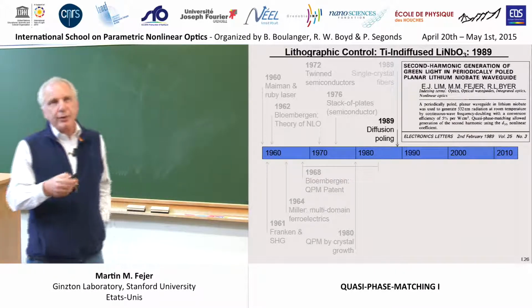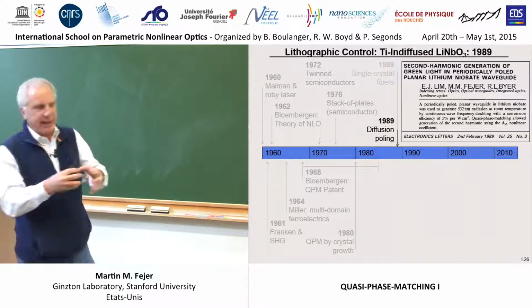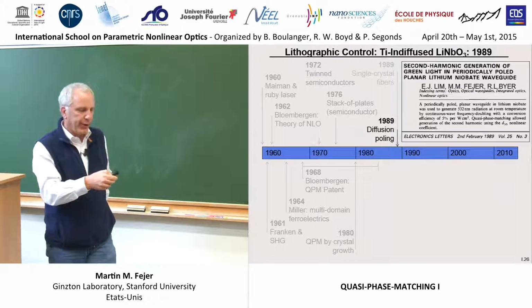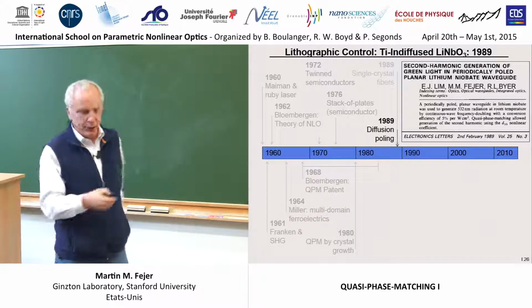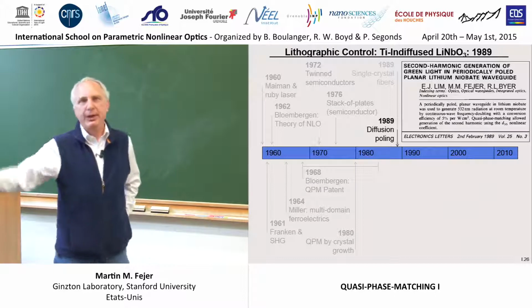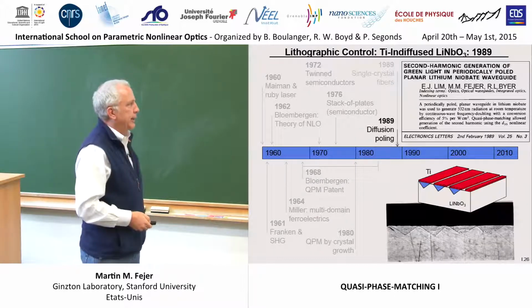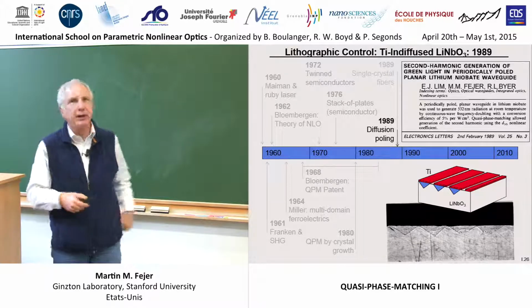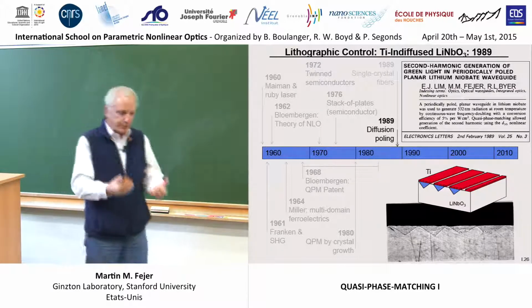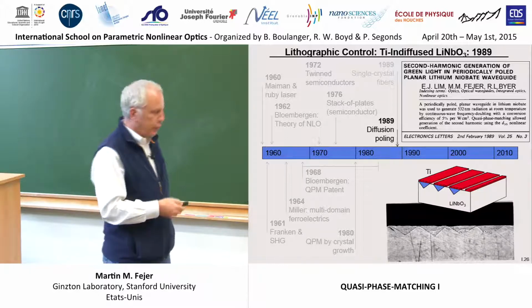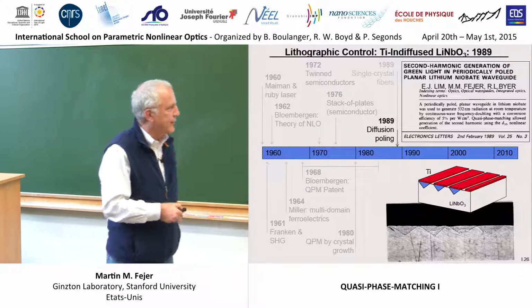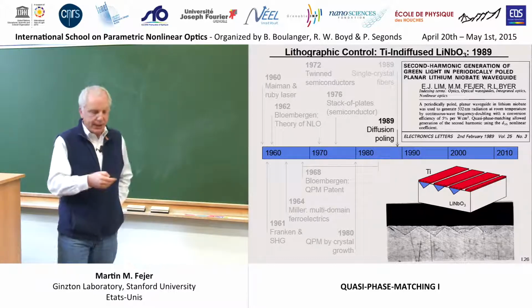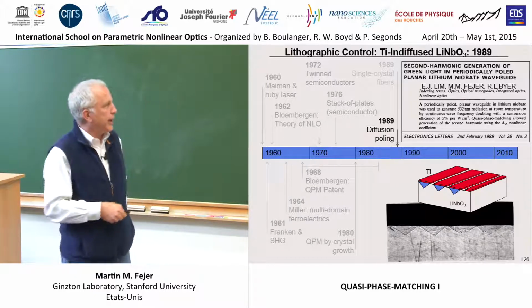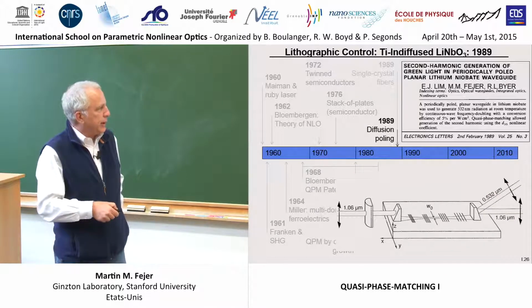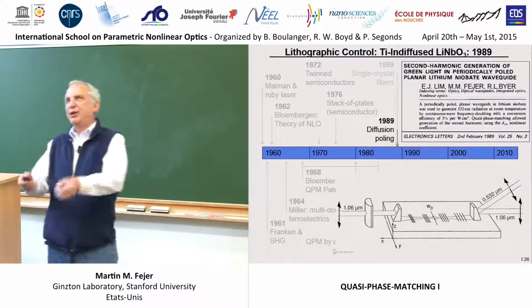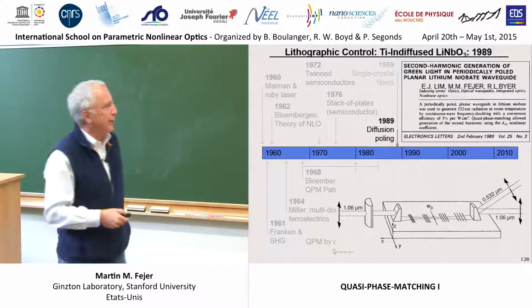The next important step was the first real lithographically patterned scheme, a method where you do photolithography to control the pattern, and hence you get long-range order as good as the quality of your photolithographic mask. In this case, diffusion of titanium into the surface of a lithium niobate wafer induced domain reversal. The physics of this is a long story and not very interesting because the technique is not really used anymore, but it allowed demonstration of a real quasi-phase matched experiment done with a real modern fabrication technique.